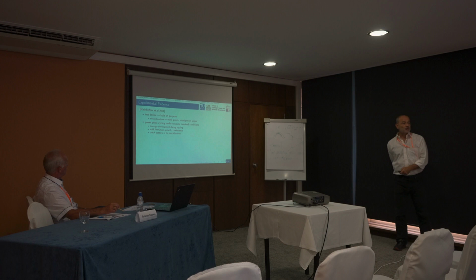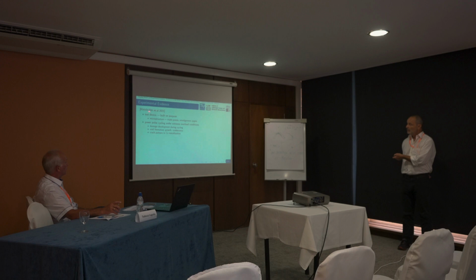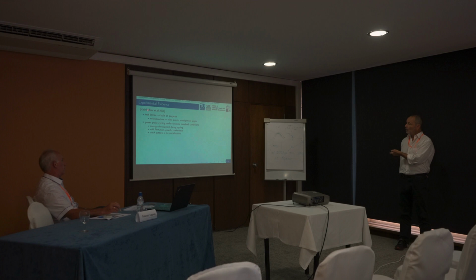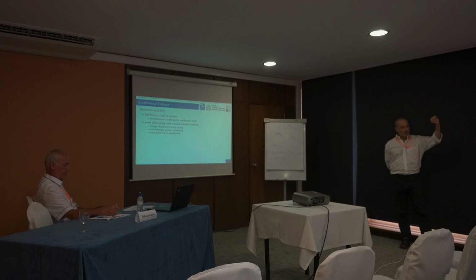What do we know from experimental testing? This is from an accompanying project, also with Infineon, but with our material scientists, that's already published. They considered a test device which was built on purpose. And from this test device, under thermomechanical cycling, we know the microstructure, the misalignment angles, and so on. So what they recorded in the experiments, the damage development during the cycling, the void formation, the growth and coalescence, and finally the crack pattern, the cross-section of the copper metallization of our test device.